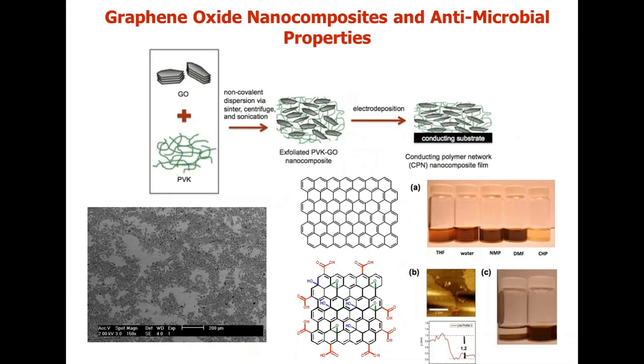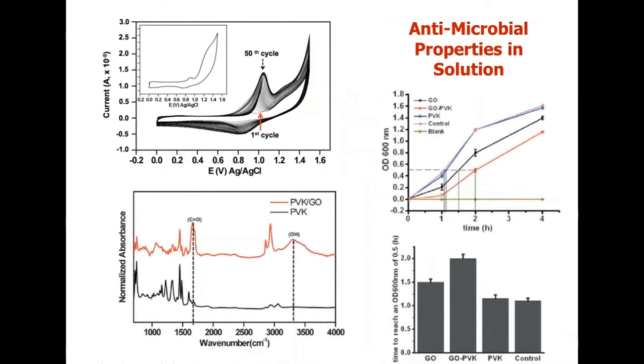Now, these films, as I mentioned earlier, can be dispersed in different solvents. This is a picture of the graphene oxide platelets that was prepared using an oxidative, exfoliation method. Once we disperse them, we can prepare them as films or as solutions. We can actually investigate their antimicrobial properties. So what we will observe is that this graphene oxide is actually capable of killing bacteria, not just preventing biofilm, but actually killing bacteria. And we know this based on the optical density measurements of the dead bacteria.